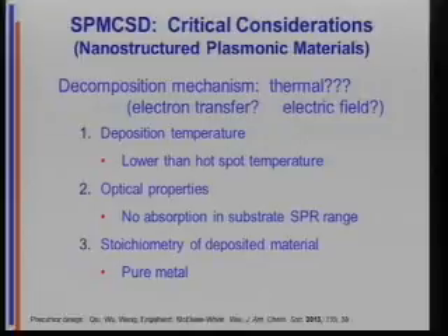All right. So I went through my same checklist of questions with David, like what am I supposed to be looking at here? I have no idea. So the decomposition mechanism of the precursor, honestly, we haven't got a clue. It could be thermal because we're generating hot spots. It could also be electron transfer because we have excited state electrons. It could be the tremendously high electric fields that are generated and associated with surface plasmon resonance. We haven't got a clue. But because I know how to deal with thermal, we're going to assume thermal for a minute. The decomposition temperature of the precursor has to be lower than the hotspot temperature. What is that? We'll come back to that in a minute. Optical properties, we want the compound not to absorb where the substrate is because it will be competing with light. And we'd like to be making pure metal because the whole idea is nanoelectronics eventually.